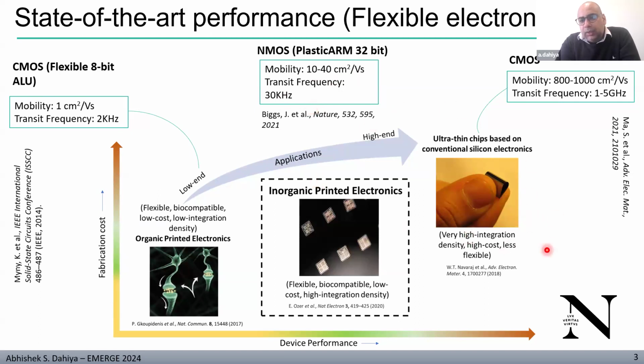And the last approach is basically we use silicon chips and thin them down to a level where they become flexible, around 35 to 50 micrometers. And then, of course, you keep the silicon performance, and that's similar to the silicon electronics we have currently.